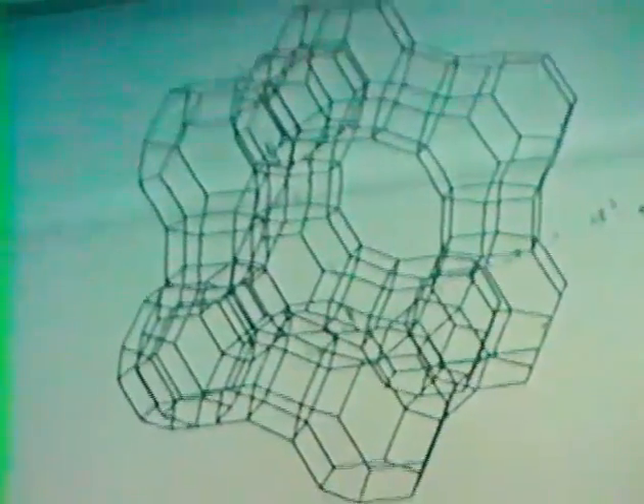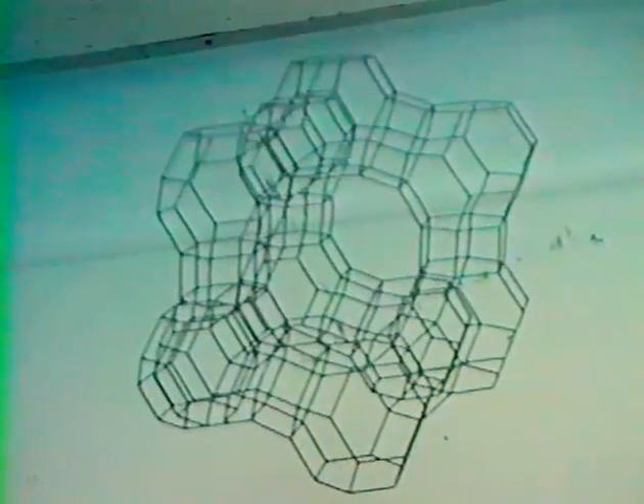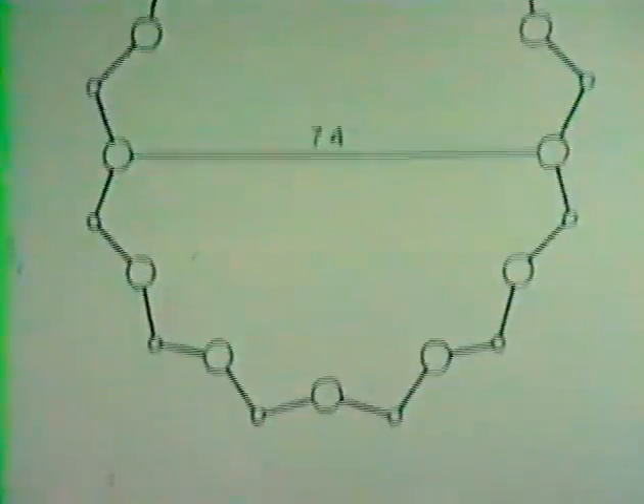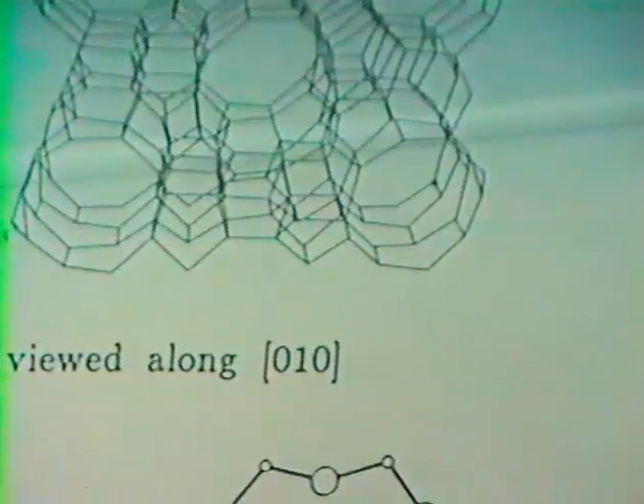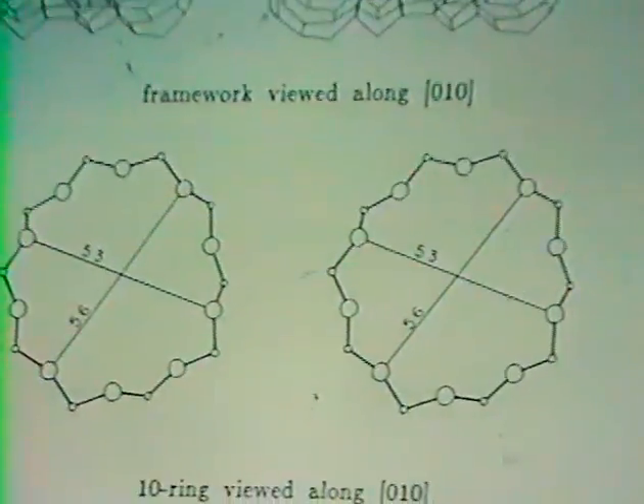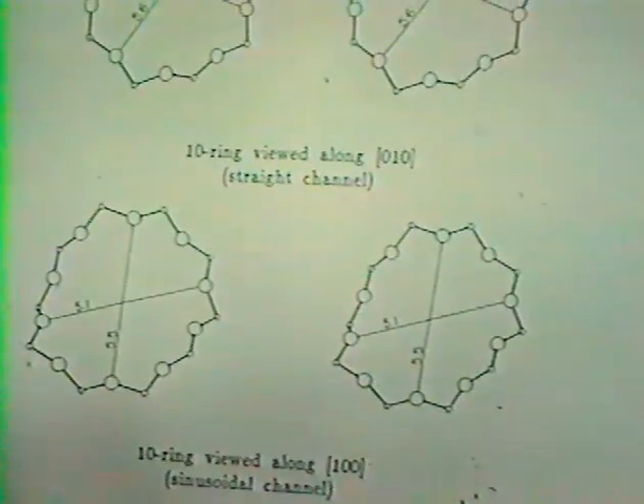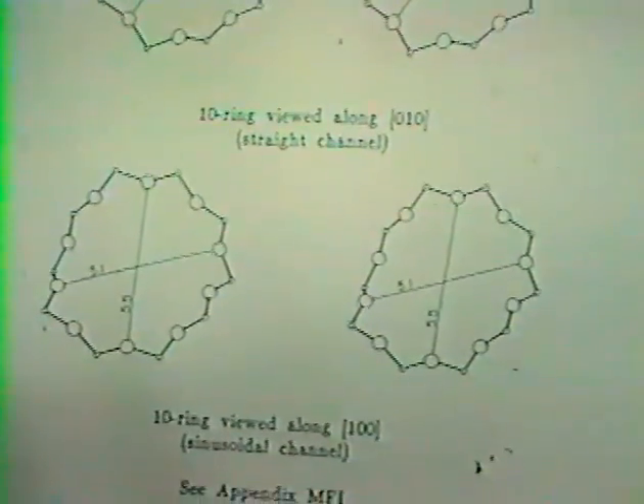This is taken from the Atlas of Molecular Sieves. For Y-zeolite, the average pore diameter is around 7.4 angstroms. If we go over to the shape-selective catalyst, ZSM5, you see that the average pore diameter is much less restricted, roughly 5.5 in each direction. We know this catalyst type of zeolite structure is specific for cracking normal paraffins, but rejecting larger molecules.